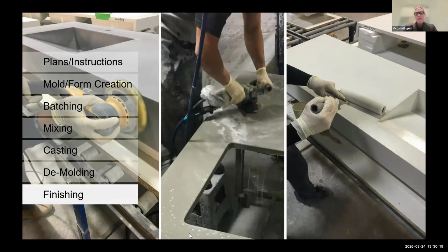The final stage in the GFRC fabrication process, and one of the most important, is finishing or processing. This is where the cured piece is refined and elevated from a rough and raw concrete piece to a functional piece. Because the visible surfaces need to be both durable and aesthetically pleasing, this step has to be taken by the manufacturer in order to yield a high quality product. The finishing process here is going to vary by fabricator and also depends on the desired application of the piece. Some fabricators prefer to retain as much of the concrete's authenticity as possible, perhaps doing some light sanding, and that's it. Others are going to choose a far more labor-intensive process.